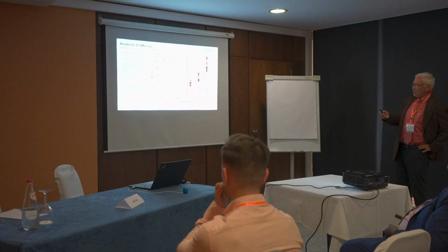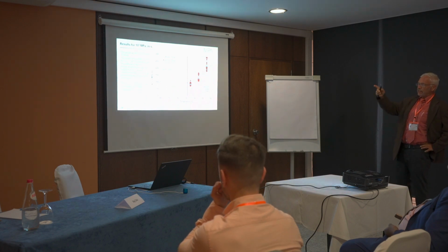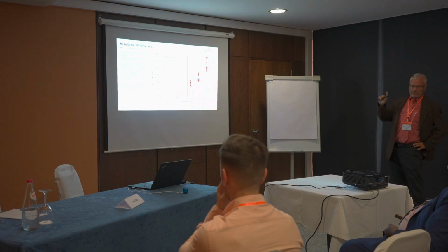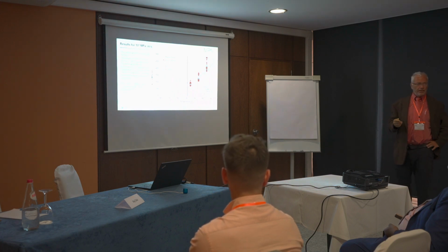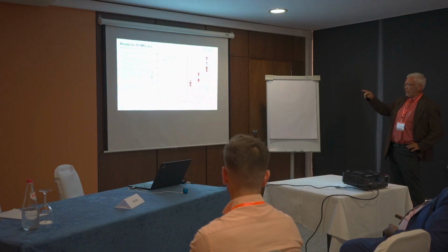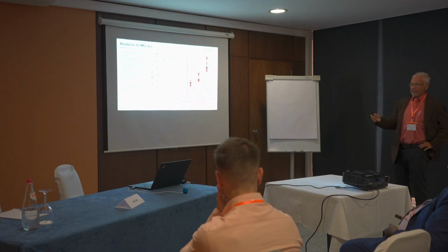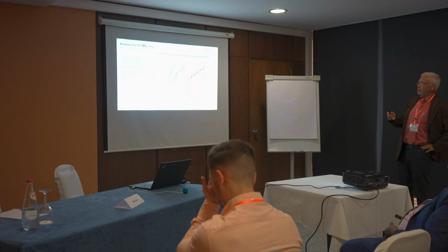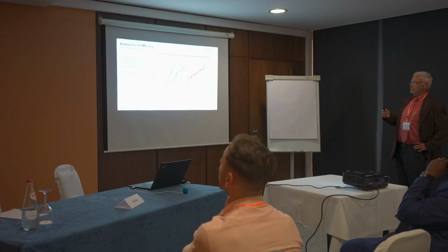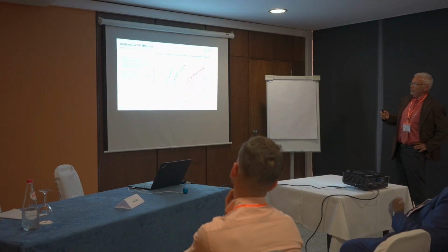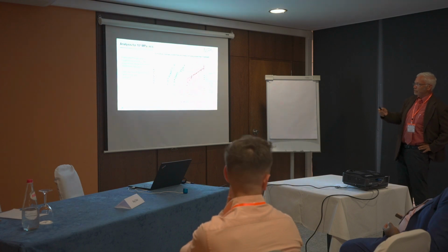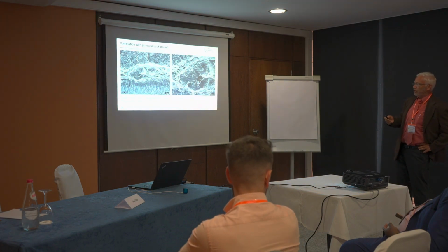And the effect is increasing if we go to 10 to the 4th, and 10 to the 4th is the rate where the temperature increase at the crack tip starts to grow. So we have both effects, crack arrest and the temperature increase. So these are the analysis of the probability for 10 to the 4th.